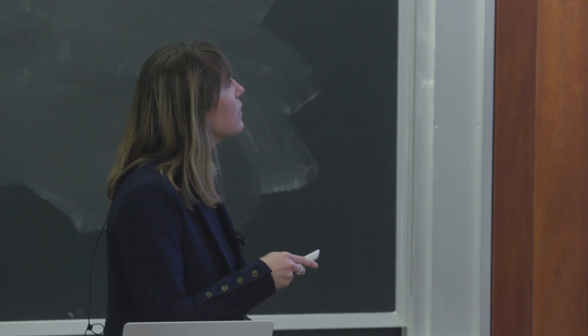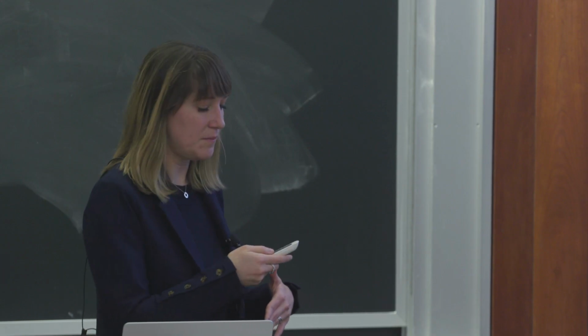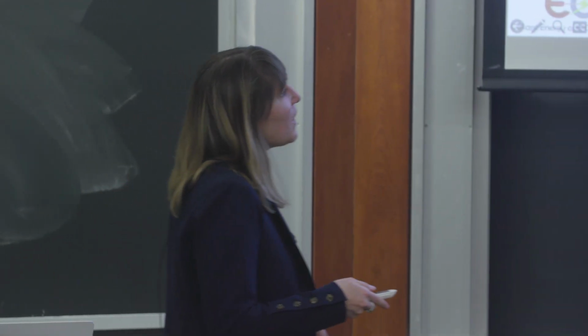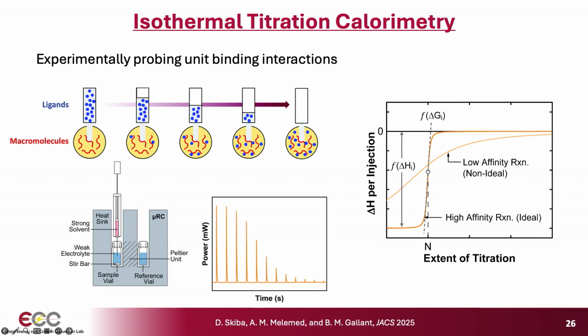And the ligand will undergo a binding reaction with the macromolecule and absorb or release heat. And we measure that as the power that the calorimeter requires to retain the sample vial under isothermal conditions with respect to the reference vial. Okay, so from this, we can directly determine the enthalpy of the interaction. And so in a high affinity reaction, like you have with many biological interactions, you'll get this type of a profile here that maps the delta H per injection over the extent of the titration.